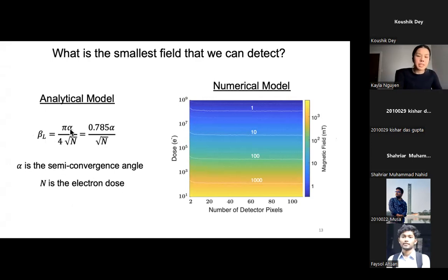Alpha is very interesting. We're alpha limited because we're turning off the objective lens. And so alpha is on the order of a couple of hundreds of microradians. For a spatial resolution of 4 to 5 nanometers, we can detect millitesla fields in our numerical model.